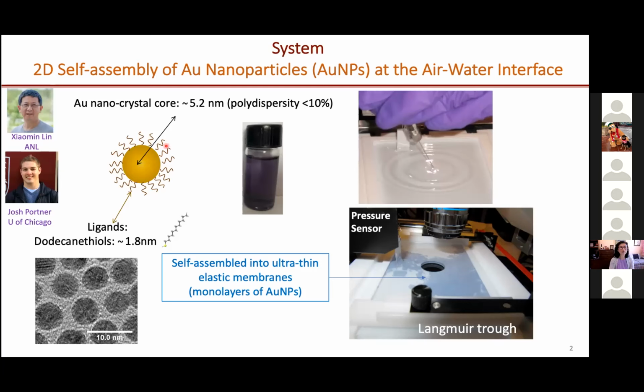The core size of the nanoparticles is about 5.2 nanometers. They're quite nicely, narrowly distributed. They have dodecane thiols as a ligand, and they disperse in organic solutions. When you spread them on the surface of water, they form nice nanometer-thin monolayers.